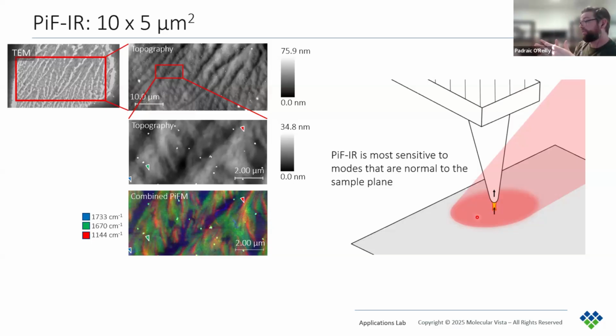Our stage accuracy is really good. It's sub-micron, and we're trying to improve that as well. But with the coordinates themselves, we don't know if there's a subtle variation in those. So I would say we can do the scans probably at the moment about 30, 40 seconds for topography, and then we do the PiFM spectra as well. We can do them in 5 to 10 seconds. Obviously it's not super quick compared to some other techniques, but I would say it's not bad as AFM goes.